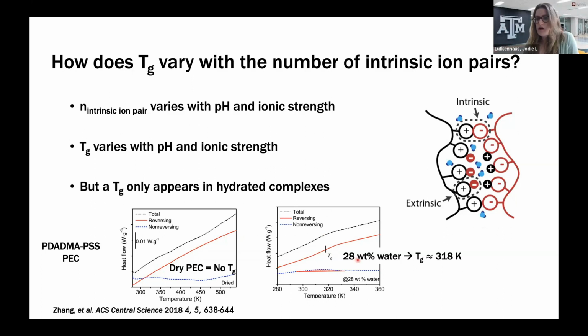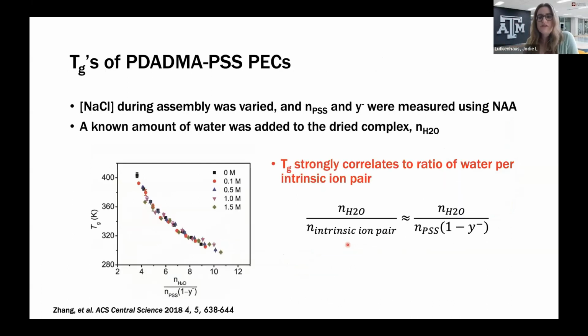But if we add some water, 28% water, look in this red non-reversing curve, we have the appearance of a glass transition. And what we've seen is that the glass transition will move around depending on how much water is in there, also how much intrinsic ion pairing you have.